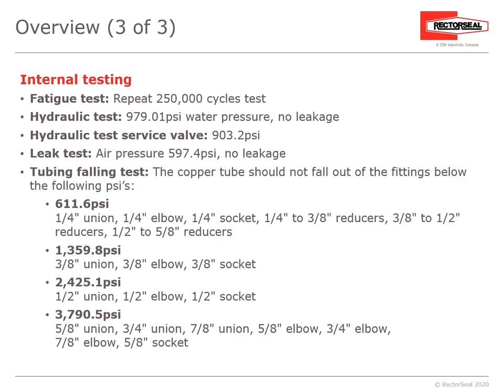A hydraulic test, 979.01 psi water pressure, no leakage. And then a hydraulic test on the service valve, 903.2 psi. The leak test, using air pressure, 597.4 psi and no leakage. And then we have the tube falling test. That is, the copper tube should not fall out of the fittings below the following psi's. And again, that's going to vary based on the diameter and the fittings.